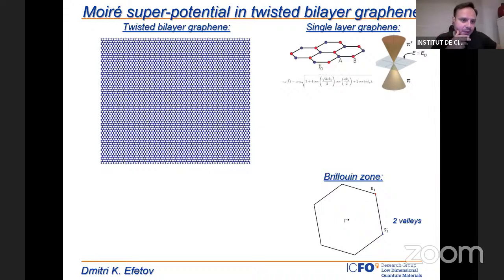And just to explain in slightly more detail how twisted bilayer graphene works, basically we start with a single graphene sheet. And again, as you can see, this is this hexagonal lattice of carbon atoms in 2 dimensions. For such a lattice, we can perform simple tight binding calculations, where basically the band structure is defined by the 2 carbon atoms, A and B, which define the unit cell. And we can just define a hopping term between A and B lattice sites, gamma 0. And solving this tight binding approximation in the low energy limit really gives us this linear band structure. And that just means that graphene is a semi-metal, or in other words, a Dirac metal, and electrons behave like massless particles. And this is, again, all well known from graphene.